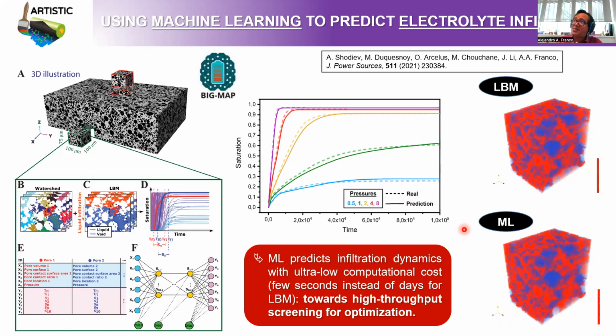The advantage, once again, of this surrogate model based on machine learning is that it can make predictions in a few seconds instead of the couple of days that you need with LBM. And this is why we believe that this surrogate version of the infiltration model can really pave the way towards high throughput screening to find the optimal conditions to infiltrate electrodes in a proper way, I mean, to maximize the wettability of electrodes with the liquid electrolyte.